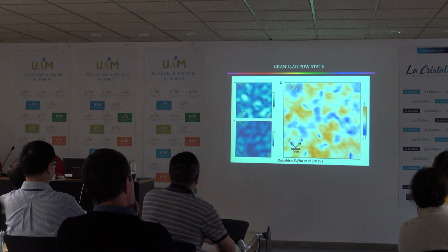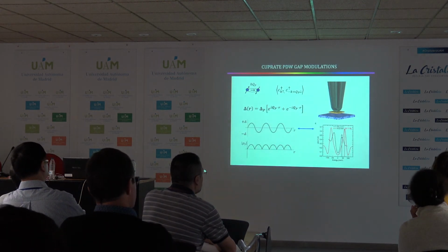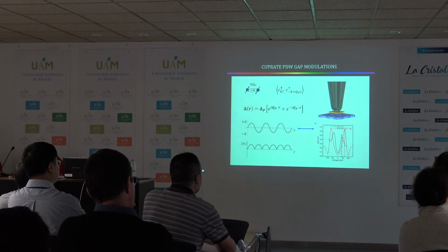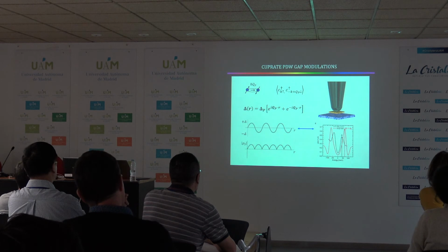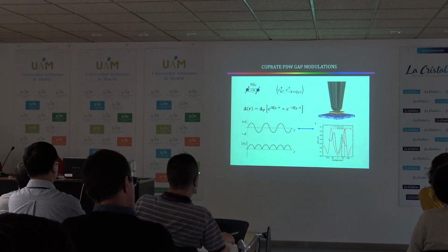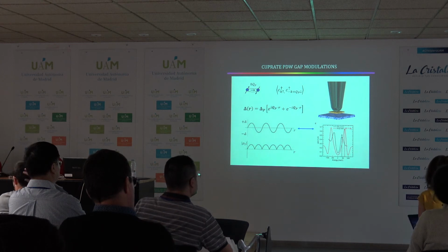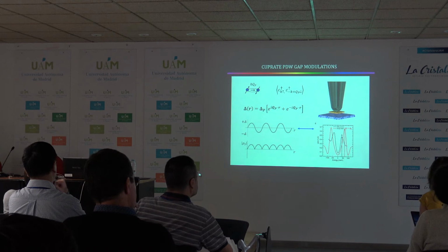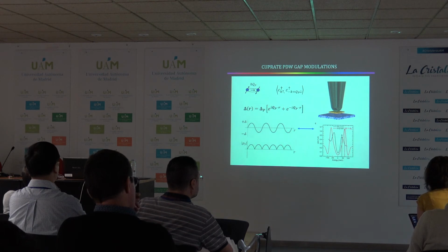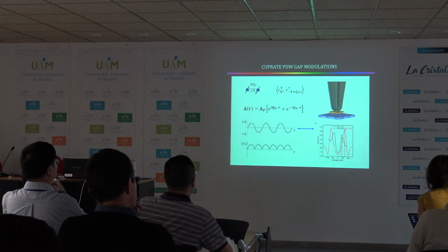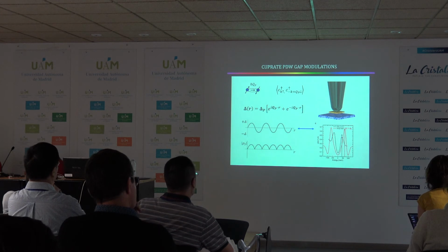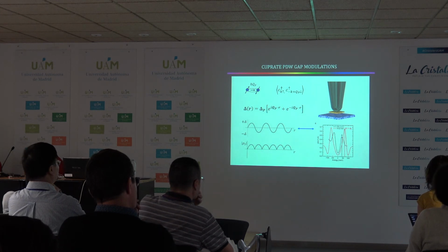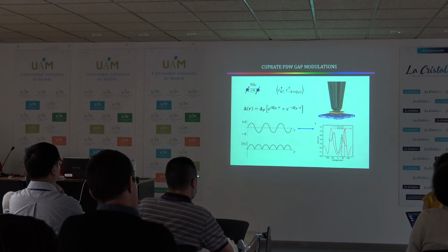Yeah. That's what I was trying to do with this diagram, but thank you very much for the question. So, there are 3 classes of phenomena that we have been working on. One is the density of C-dagger, what I call the superfluid density, which doesn't modulate. We detect that by Josephson tunneling. Another is, does the energy gap to single particle excitations modulate? For some reason we don't understand, this has been very hard to detect by previous techniques, but with this technique, it's quite clear that the gap does modulate. And the third thing we were using is the Q, 2Q effect. The only real data in the vortex core is the Q, 2Q effect, and it's sitting on top of Ginzburg-Landau theory in order to deduce that it's a pair density wave.